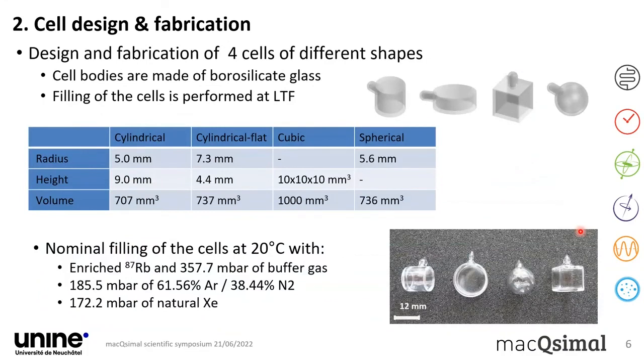This brings me to the cells we did in this study. Here you can see the design of 4 different cell shapes that we developed. The bodies were made of borosilicate glass, and we have a high cylindrical, a flat cylindrical, a cubic, and a spherical cell, where we aimed to have approximately the same volumes inside, and we performed the cell filling and production in our facilities here at the university. And down here on the right, you can see the final cells produced with the rubidium and the vapors.